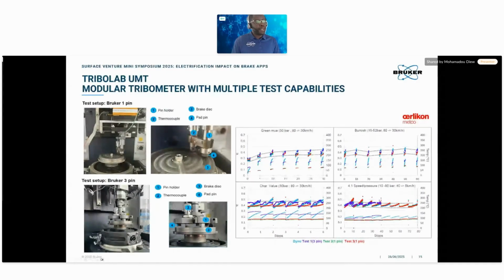When we run this testing, we run it in two configurations, one with 1-pin and one with 3-pin, and compare the results with the dyno results in blue. As you see underneath, we have 3-pin in contact with the sliding thermocouple that measures the temperature. This will show us the evolution of the temperature during the test.